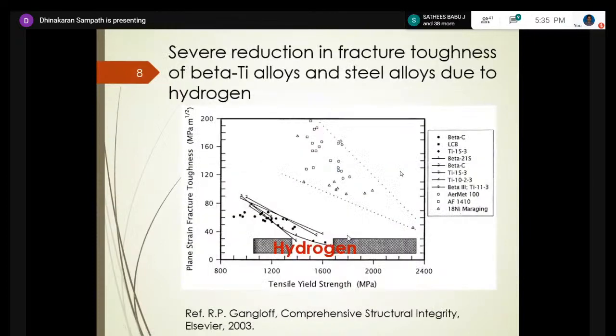So that's one key driving force to pursue this research, and to come up with hydrogen embrittlement resistant alloys. And here I'm showing another interesting graph where we are seeing plane strain fracture toughness, which is measured as stress intensity factor in the units MPa root meter. What this parameter means is the ability of the material to resist unstable cracking. Once it reaches this kind of stress intensity, it will fracture until it becomes two pieces.